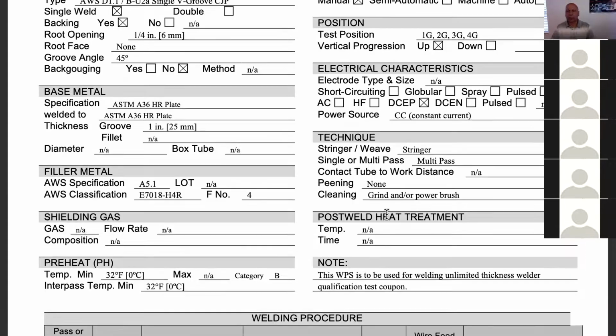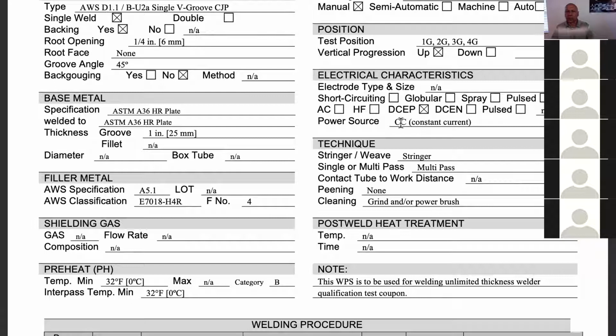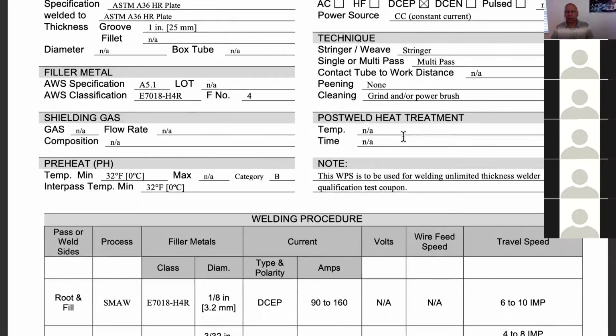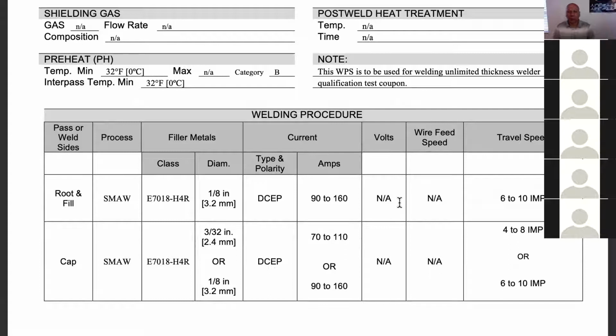according to the arc length in a constant current machine. Remember that we put a constant current machine to be used here, which means the volts are automatically adjusted by the machine depending on how the welder holds the arc. If a short arc is being produced, then the machine would drop the voltage so that we don't get an excess amperage going across the arc. If the welder decides to long arc it, then the machine will turn up the voltage automatically to be able to get that many amps across the arc. A longer arc produces more resistance. All right, so the travel speed is going to be more or less suggested, but on average 6 to 10 inches per minute